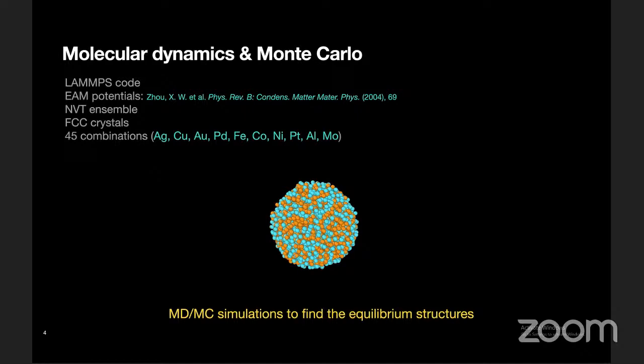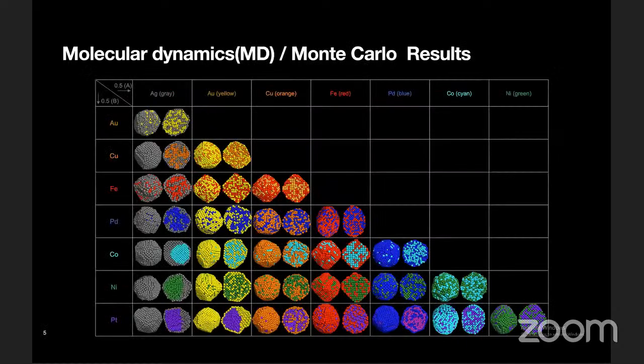In order to answer these questions, we used molecular dynamics for 45 different bimetallic combinations composed of these 10 metals. As we were interested in the equilibrium structures, we started the MD simulations from a bimetallic liquid drop at high enough temperatures and cooled it down to room temperature. And to make sure it reaches the equilibrium state, we continued the simulations with Monte Carlo until they formed nice crystalline structures. And this is some of the simulation results.